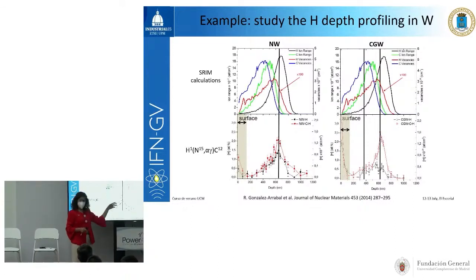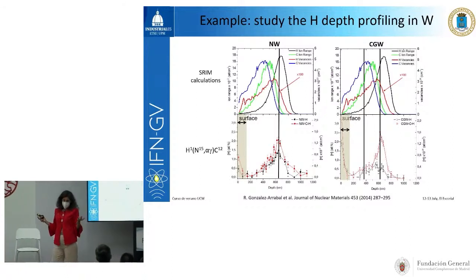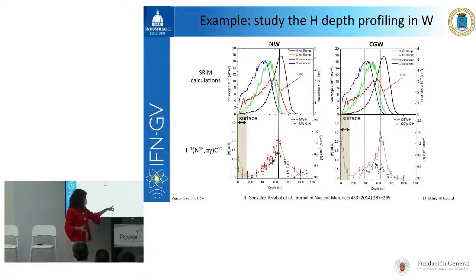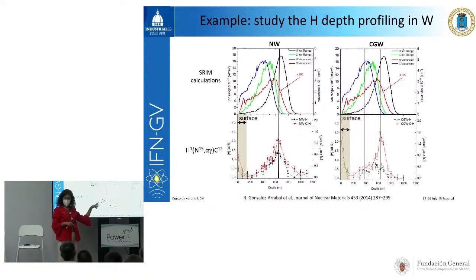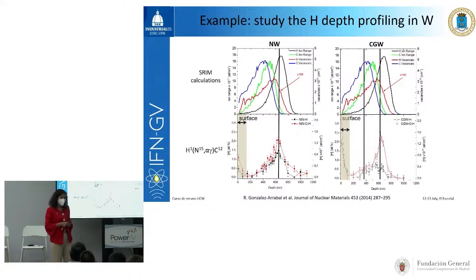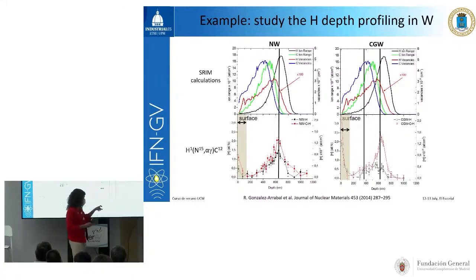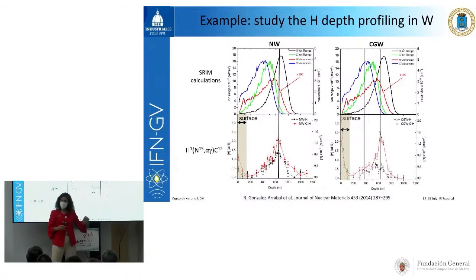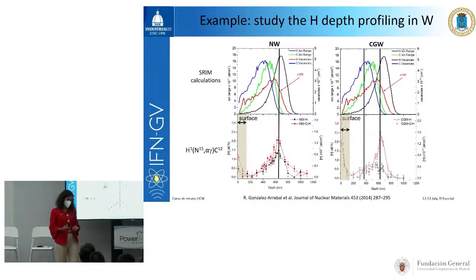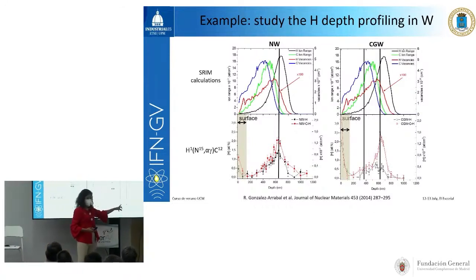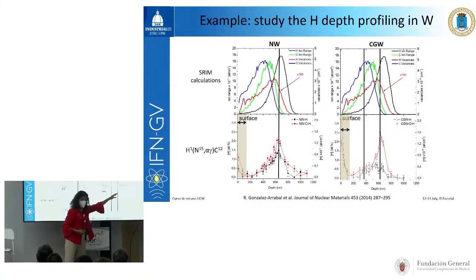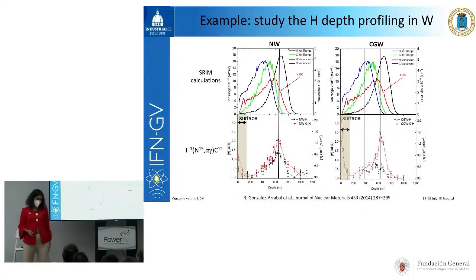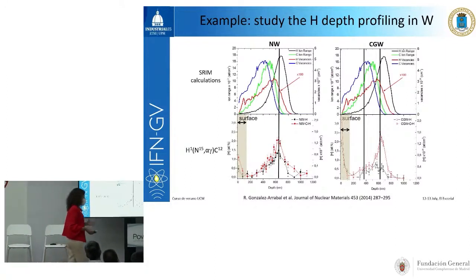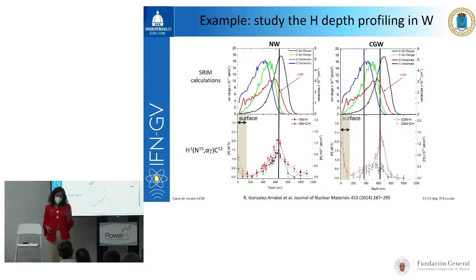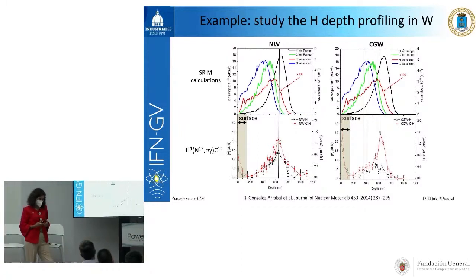What we observe is that in nanostructured material there is no difference between the sample without vacancies or with vacancies; both curves are almost the same. But in the coarse-grained sample, the commercial sample, we see a very large difference when we introduce vacancies before irradiating with hydrogen. You may see that the hydrogen content is strongly increased. So, this result is very hard to interpret by itself.